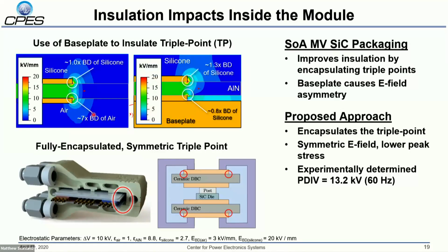Once we encapsulate both sides, we're now on the order of 1.3 times the breakdown strength of silicone and about 0.8 times the breakdown strength of silicone. So we're getting closer to the safe region, but one of the problems this base plate causes from an insulation standpoint is it causes an asymmetry in the formation of the electric field. And you can see that with these relative breakdown strengths. So by removing the base plate, we also remove this asymmetry in the electric field.